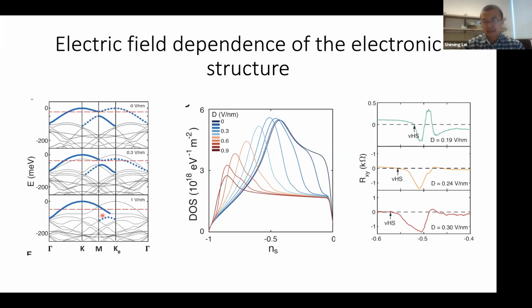I see. For WTe2, although it's not graphene with such nice, beautiful C3 symmetric stuff, if you twist it, you can also form that kind of line shape in transport. But then the in-plane anisotropy can change dramatically, actually. I see. The second question is for the WSe2. Sorry, I think I somehow missed the part: which phase is this, 2H phase or 1T prime phase? This is the 2H phase, so it's a semiconducting phase. Yes. I see. And do you expect anything new for the 1T prime? I mean, that will already be a semi-metallic phase.